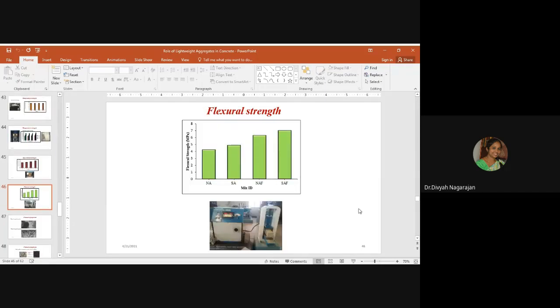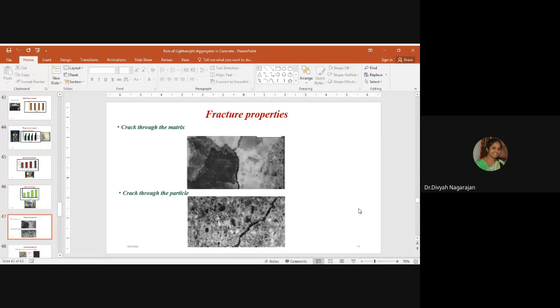Flexural strength. The flexural strength of the aggregates was also found out, and the addition of fiber improved the flexural strength. Sintered fly ash aggregate concrete without fiber also had around 1.5 times more flexural strength when compared to the normal concrete. Fracture properties. Coming to the fracture properties, observing the cut section of the specimen, it can be seen that the crack had occurred through the matrix, and the second picture shows the crack through the particle.